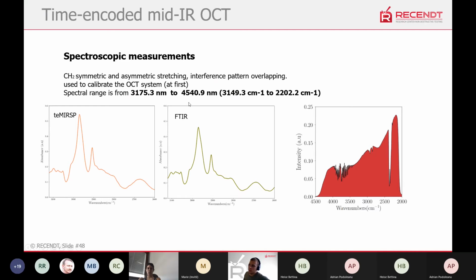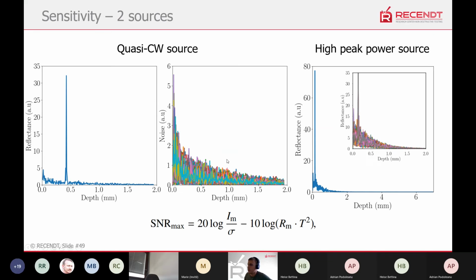Some spectroscopic features: this is the absorption of PET polymer recorded with this time-encoded system, and this is with a Fourier spectrometer, a commercial and quite expensive one. I would say it's difficult to say which has higher resolution and what is better actually. It performed quite well, and these features are used to calibrate the system.